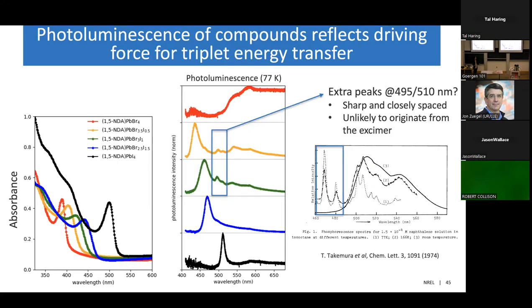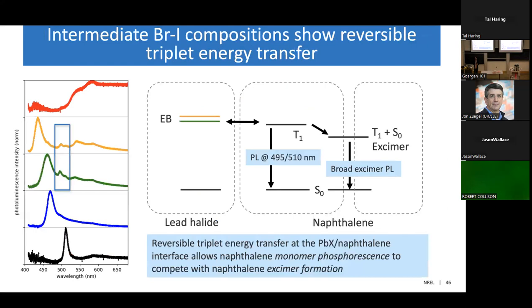Now, if you had sharp eyes, you might have noticed there's actually two extra peaks that have popped up in the spectra for the orange and the green curves, located at around 495 and 510 nanometers. The fact that they're so sharp and closely spaced means that they're unlikely to originate from an excimer, which tend to have really broad, unstructured spectra. And if we look in the literature, the location of these peaks is actually an exact match with the monomer phosphorescence from naphthalene. And if we go back to the energy band diagrams, we can understand what's going on here.